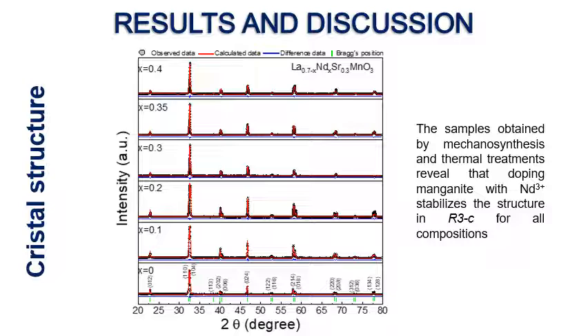In the perovskite structure, the A site is occupied by alkaline and alkaline earth ions, and the ion transforms the crystal structure according to the difference in ionic radius. The B site, occupied by the transition elements, confers the magnetic properties of the material. The magnetocaloric phenomenon works when the material is subject to variation of the magnetic field. The ordering and disorder of the spins in the material confer these changes of entropy, in a material with a change between ferromagnetic and paramagnetic phase at a temperature around the Curie point.